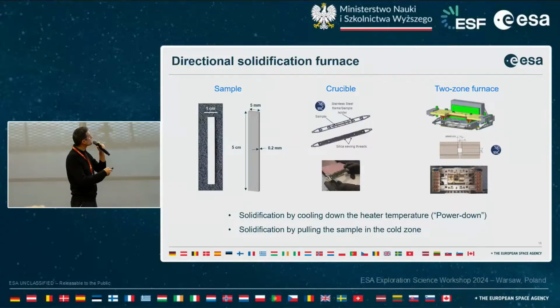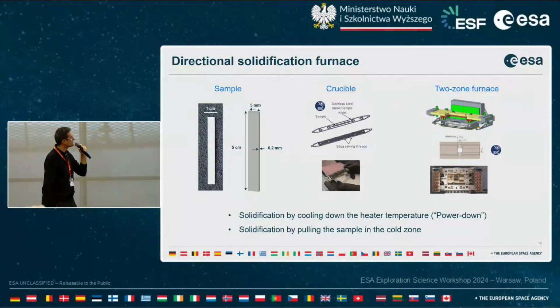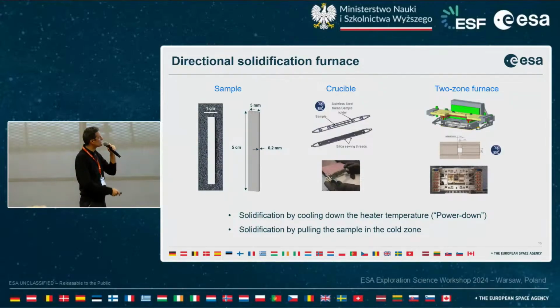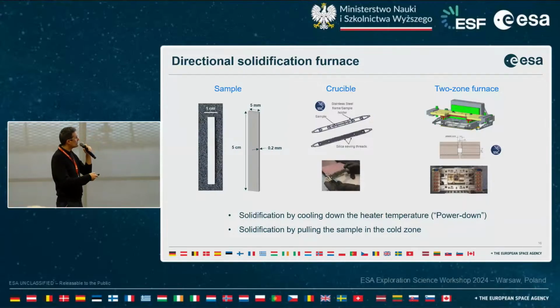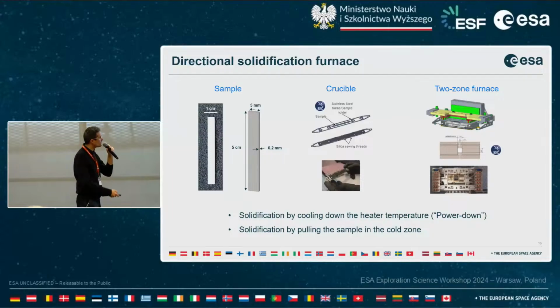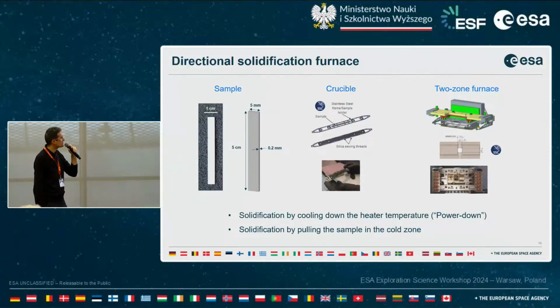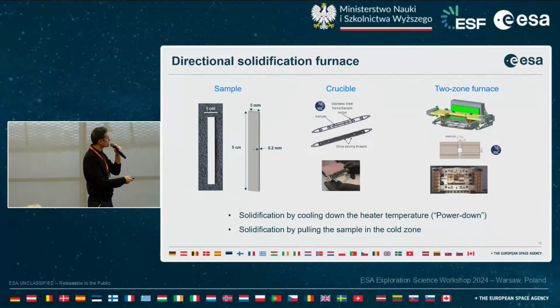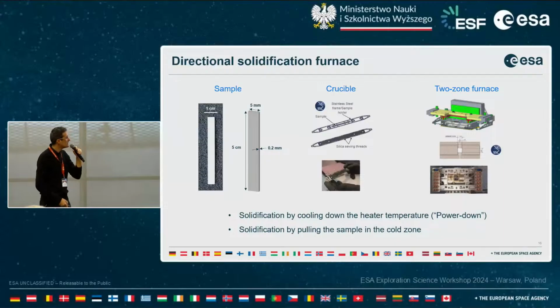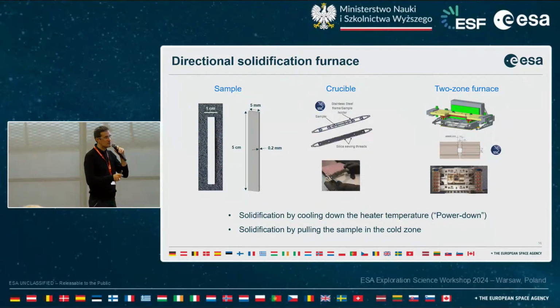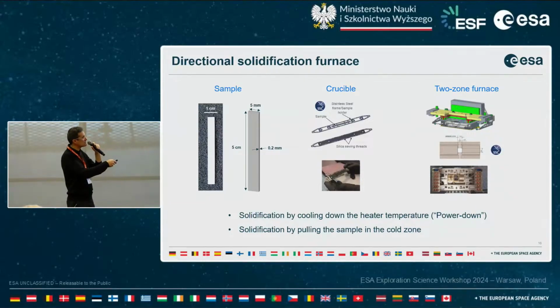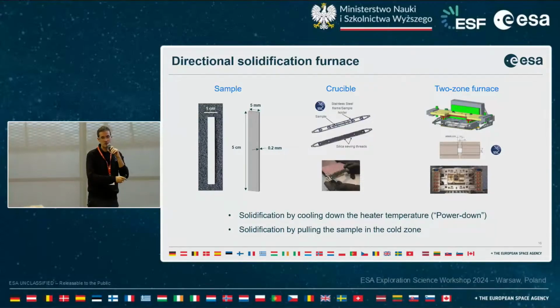Here, just to show you what it looks like, the idea will be to study thin samples in order to have sufficient X-ray transmission. You can see here pictures of this new two-zone furnace device. Again, it will be directional solidification, with solidification triggered by cooling down the heater temperature, which is what we usually do when carrying out X-radiography experiments. What is also interesting is that it was implemented to allow pulling experiments. It will be possible to move the sample inside the furnace in order to study it not only on the 5x5 field of view, but along a longer distance. We will only see the top of the solidification front, but we will see its evolution over a much longer distance.